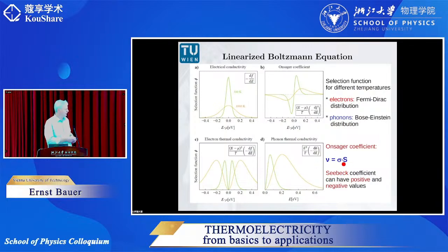The Onsager coefficient, please note, is nothing else than the Seebeck coefficient multiplied by the electrical conductivity. So the electrical conductivity is simple here, but then you can see that the Onsager coefficient, and thus the Seebeck coefficient, varies a little differently in comparison to the electrical resistivity. Because the first derivative, or the entire quantity here, shows that it is an uneven function. That means if the Fermi energy is slightly shifted above zero, then we have positive contributions, meaning that the Seebeck coefficient will become positive. Or if we have energy slightly below, then you can see everything is negative.